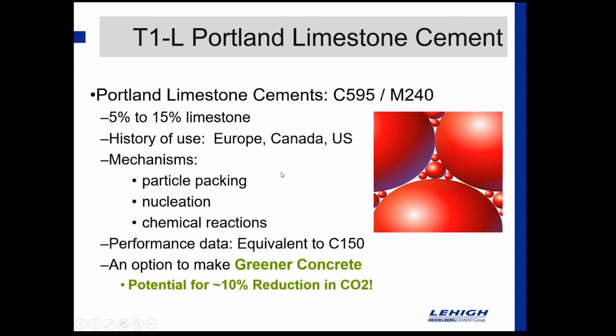And really, the highest benefit, I think, going forward is that using Portland limestone cement provides an option to make greener concrete. There's a potential for 10% reduction in CO2, and that's all accomplished without any special system or addition to a ready mix plant. There's no hardware that has to be installed or anything like that. It's simply swapping your powder out from a type 1 or a type 1-2 and replacing that with the type 1L cement, and you begin to realize that 10% reduction.